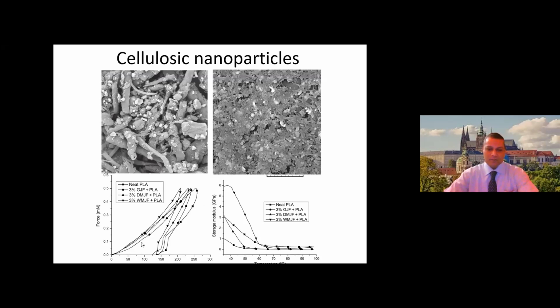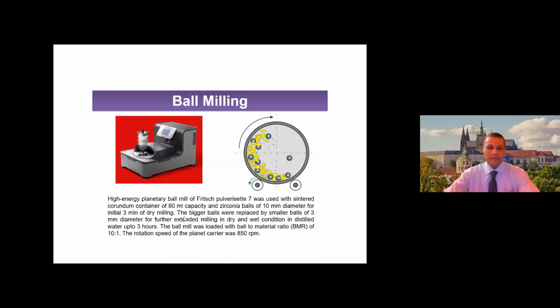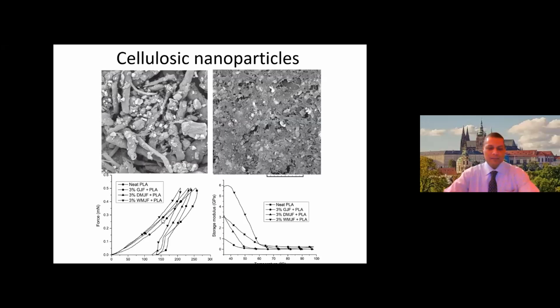nanoparticles of cellulose. In some research, the nanoparticles have been used in polylactic acid composites, and the mechanical performance has been enhanced at nano level, micro level, and macro level. There are techniques to measure the mechanical performance at nano level by so-called nano indentation, and nano indentation proves that the modulus of elasticity increases as we add up to 3% of nanoparticles.